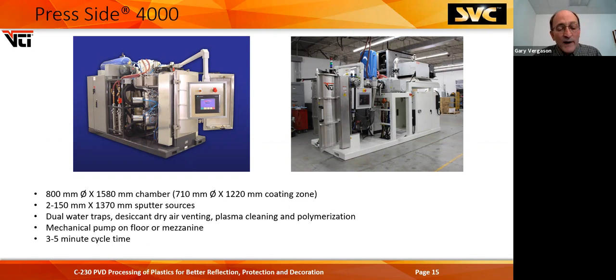Mechanical pumps are located either on the floor or on a mezzanine like you see here. And one of the key things that we learned early on, the closer we could put the roots blower to the vacuum chamber and have a little bit of a vacuum accumulator between the roots blower and the mechanical pump, sped up that roughing time. So these machines, a little over a cubic meter in volume, pump from atmosphere to 100 millitorr in about 25 seconds. So it kind of smokes. In this machine, depending on your maintenance, cycles door to door in 3 to 5 minutes.